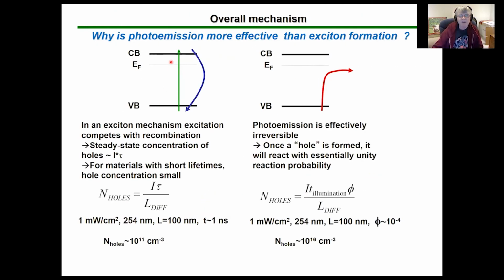Now, I simply want to contrast that there has been a lot of work in other semiconductors like silicon, showing that you can photochemically graft molecules onto those surfaces. And one can imagine that maybe there's a competition where if you excite above the band gap, you create holes in the valence band. I'm arguing that in the case of diamond, at sub-band gap wavelengths, this can't happen, but yet this process can, directly going to an electron acceptor that for some reason is not showing up on the slide.